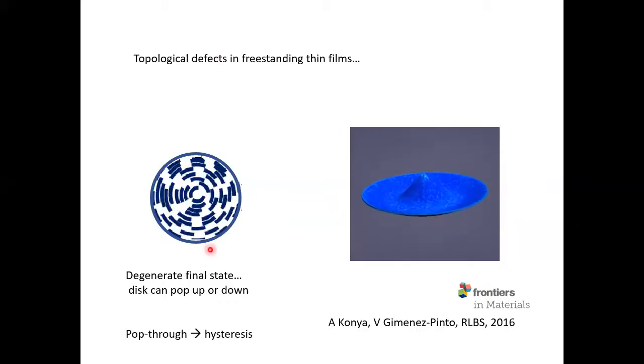So if we have a topological defect in a freestanding thin film, okay, so here's that little disc. And let's see, is this video running? It is. So as it turns into a mountain, it doesn't go directly from a disc to a cone. It goes through a hat shape first with the brim. Let's see if I can get this video to run again. There we go. So you can see because it has a finite thickness, as it's deforming, it goes first to a hat with the brim, and then the brim flips down, and the material eventually ends up as a cone shape.